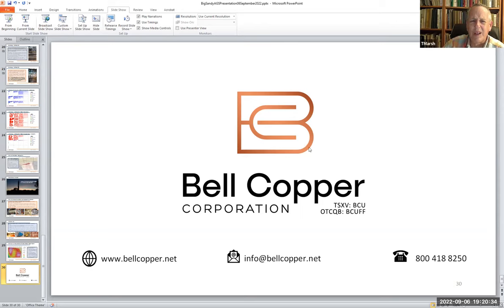Thorny Rogers, the pros and cons of MT. The frequency of the signal is so low that the depth of penetration is very great, many kilometers. Just by sitting on the same station and observing for literally days, you can get depths of investigation of tens of kilometers, even hundreds of kilometers. They study the mantle with magnetotellurics. So it's depth of penetration that's really the advantage of magnetotellurics. IP wouldn't have shown us, and hasn't. I've actually done some IP out there now, 600, 700, 800 meters depth of investigation. You wouldn't have gotten down to the sulfides at Big Sandy.